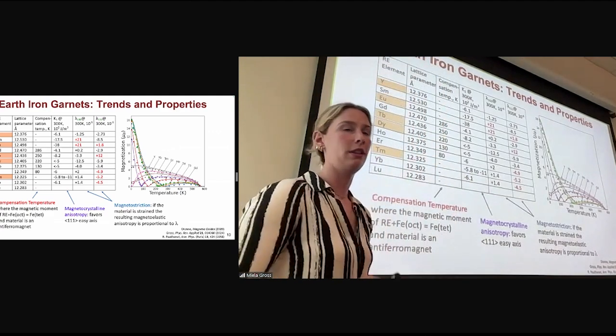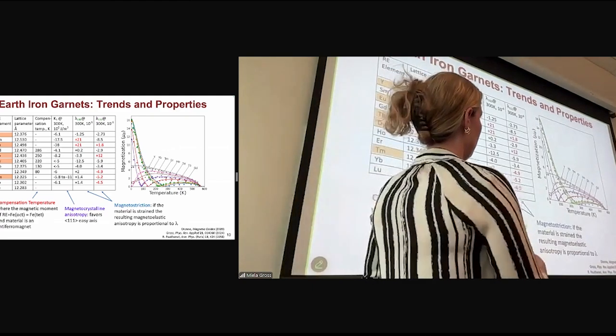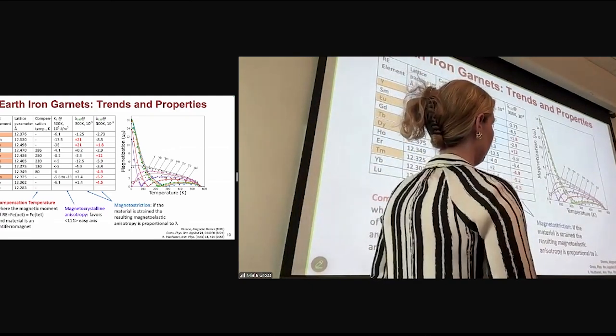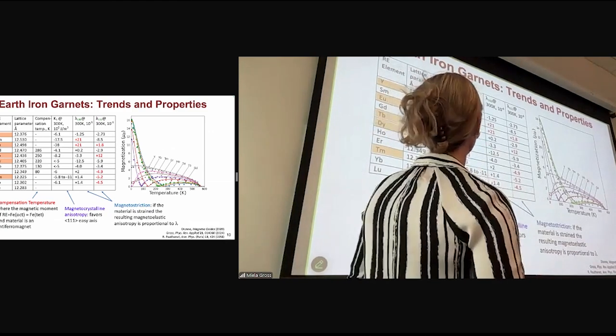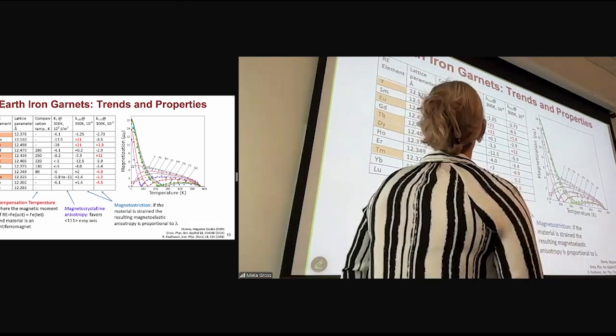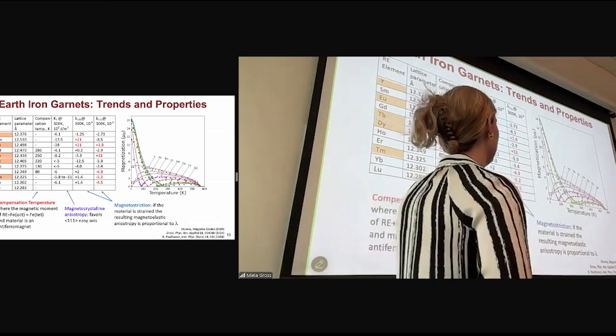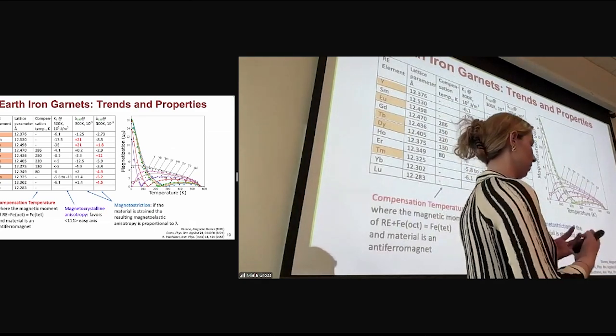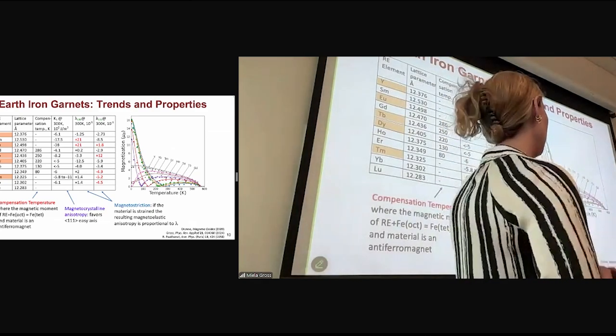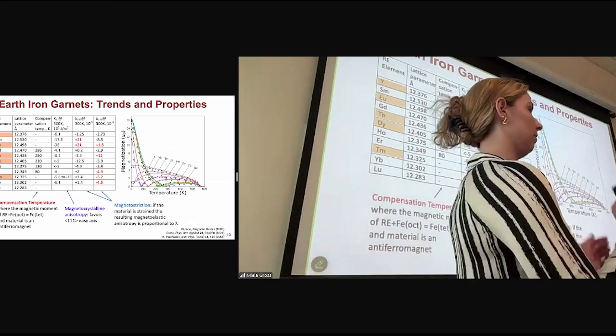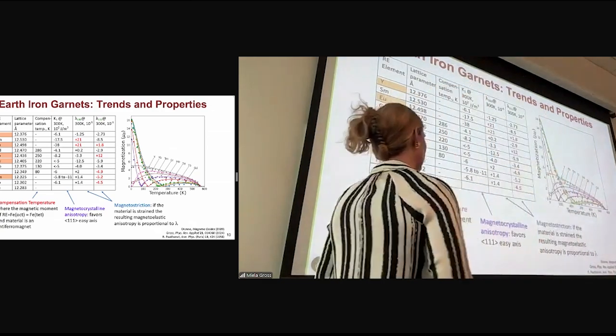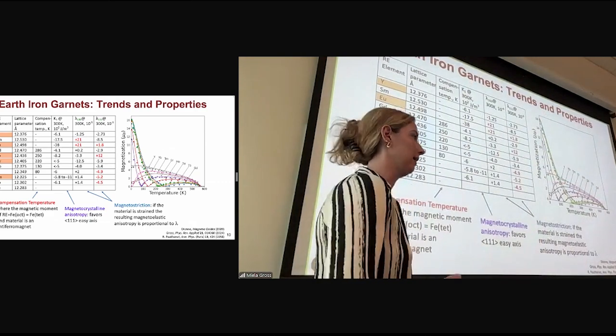And so you see on the plot on the right that the magnetization as a function of temperature really varies drastically depending on what rare earth you have in those C sites, or yttrium, for example. And some of those rare earths have this thing called a compensation temperature. A compensation temperature is basically a temperature at which the garnet has a net moment of 0 because all of those sublattice magnetizations cancel each other out. And that's really interesting for probing antiferromagnetic properties in these garnets at that specific temperature.